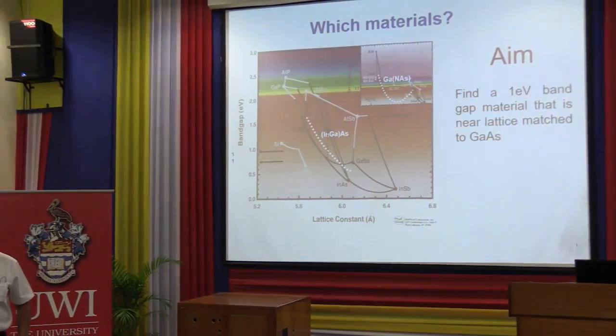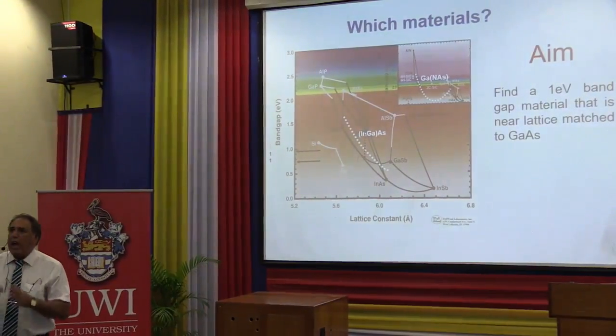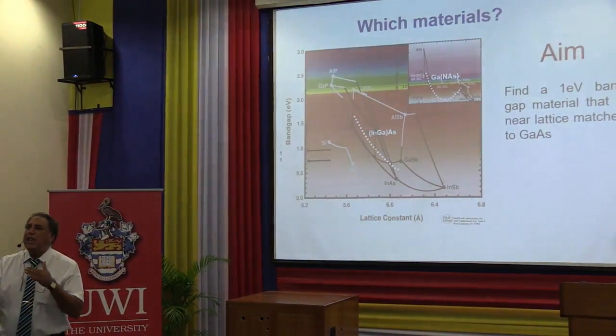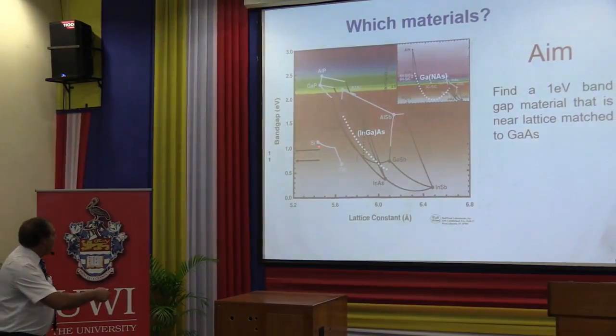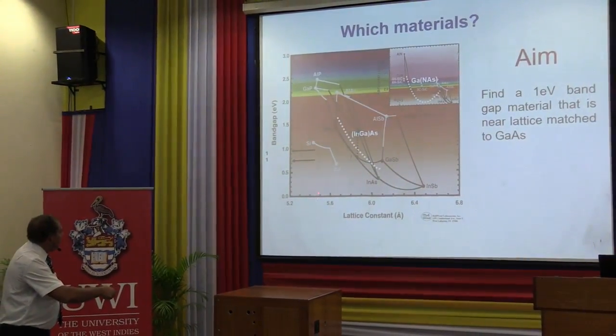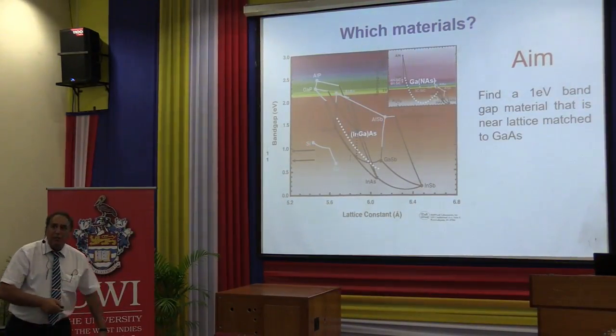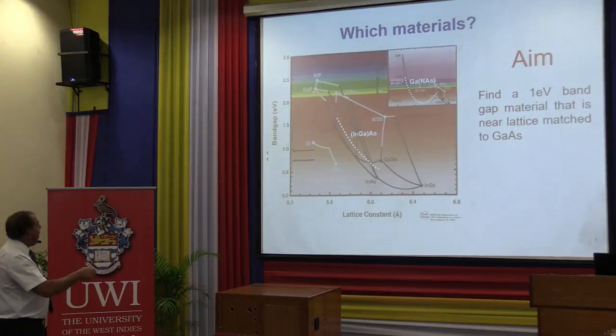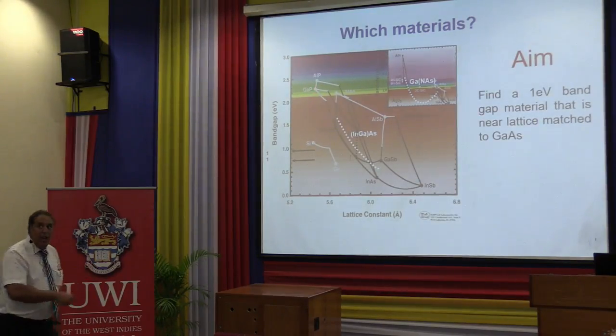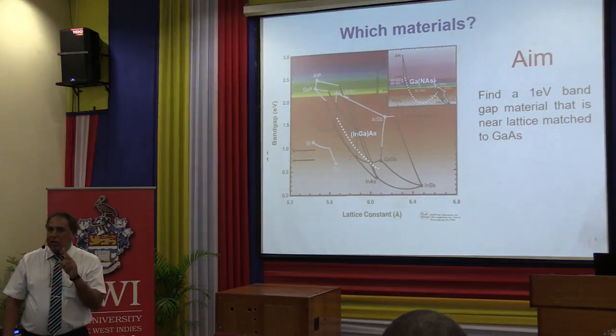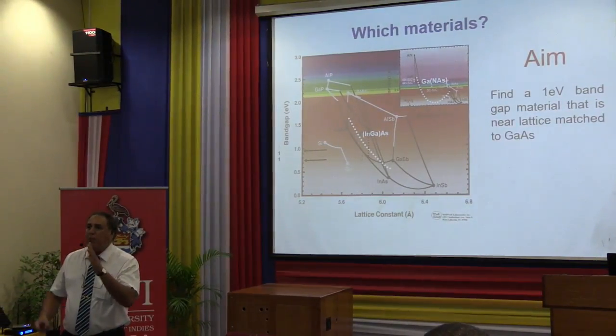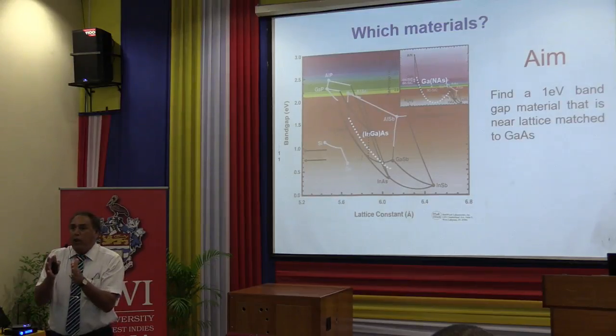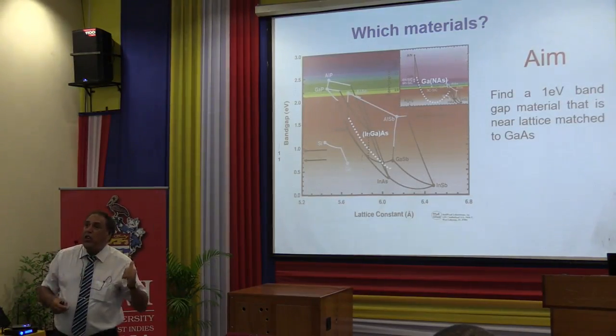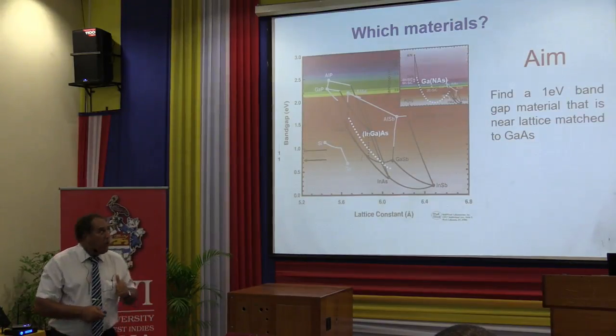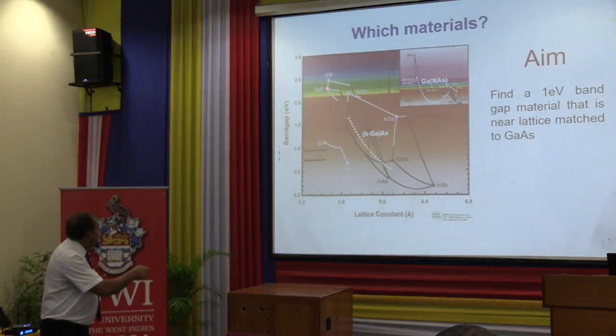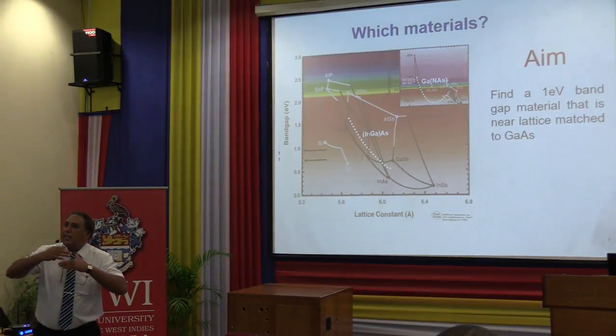Remember what I said before: when you stack materials one on top of the other, one thing you have to make sure is that they have the same crystal size. You quite rightly look at silicon here, it's this size. You don't find many semiconductors which have the same size as silicon. There's one, gallium phosphide. Can you see gallium phosphide here? It's here. So this is what we call the junction, and we're working in Nottingham on this material system, silicon and gallium phosphide, because it's just 2 junctions. And hopefully this could be good as a 3 junction or even 4 junction, because this is really tuned for the 1 eV, and this is really for the visible. So we can stack them together.